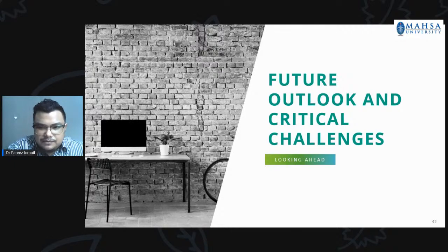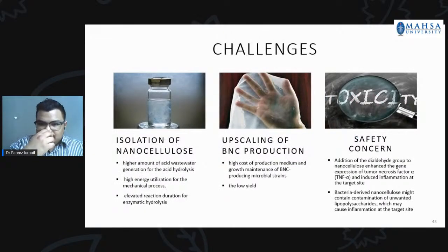And no doubt, this nanocellulose has great potential for a breakthrough of this material in various applications, especially in the biomedical industry. However, there's a challenge related to the use of these nanocellulose in this industry. First challenge will be the isolation of the nanocellulose itself. It requires a high amount of acid, which will lead to the generation of acid wastewater.